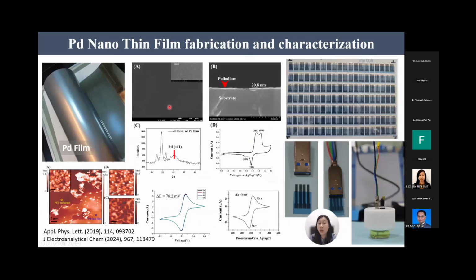So in our lab, we have a collaboration with NYCU to develop palladium nano thin film fabrications and to use it for different kinds of biomedical applications. You can see here, this is an example of a palladium film, and here shows the top view of the palladium nano thin film on the PET substrate. Here shows the cross sections, and you can see the palladium nano thin film is on the PET substrate.